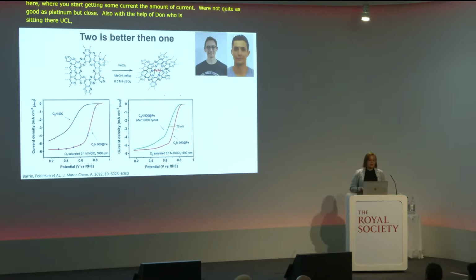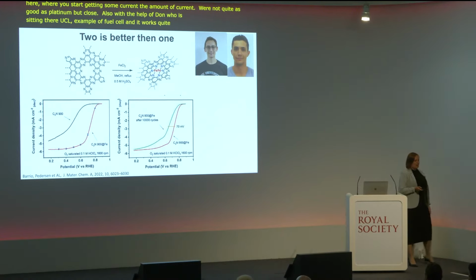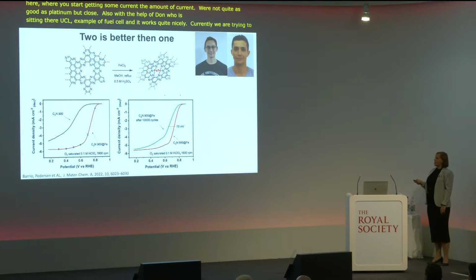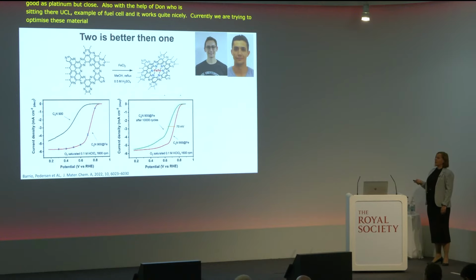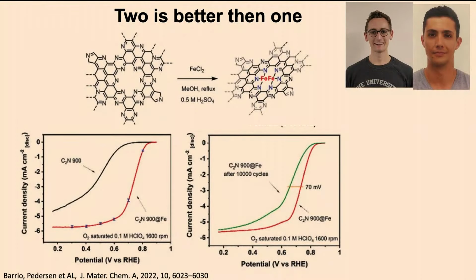And currently we're trying to optimize these materials with Angus and Jesus. They're trying, instead of one single iron, to put two irons close to each other and see how these two irons can influence the catalysis of this oxygen reduction reaction. There are a lot of intermediates involved, and that's what the catalyst does. It just breaks the linear relations between all these intermediates to get the minimum of potential and maximum current. So we're still working on this.